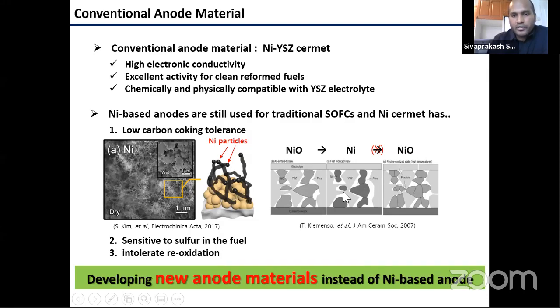In metallic nickel, the fuel cell is operated. Once we decide to stop the fuel cell and shut it down, the nickel is again converted back to nickel oxide. Because of this, the conversion between nickel and nickel oxide causes a huge volume change in the fuel cell anode, and this volume change eventually breaks the fuel cell.